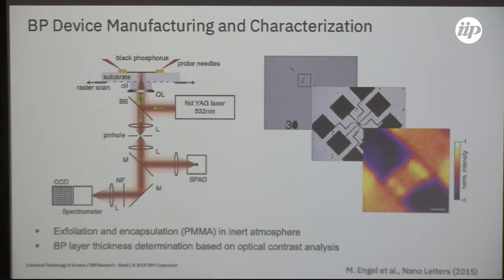Typically high-performance electronics heat up to a certain point and then the material will break, which you can see in the electronic device performance by not being able to control the device or pass a current anymore. We knew from past experience that graphene and carbon nanotube devices would break close to the contact, in an area where the heating was particularly strong. We wanted to see if we could apply the same method to study how the black phosphorus device heats when we pass an electrical current.